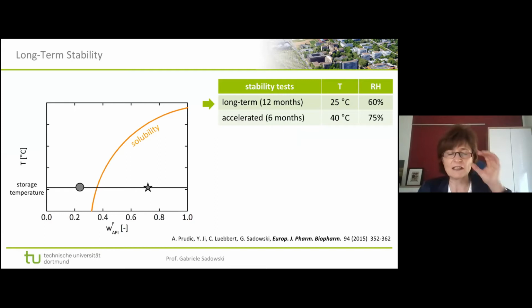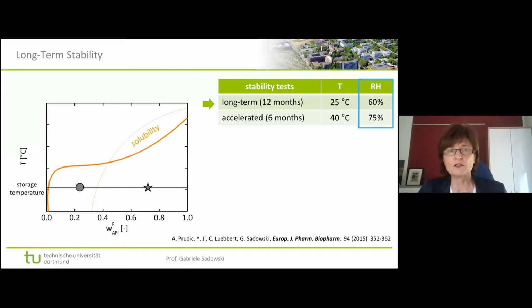And once you have water in a tablet, of course, the API does not want to be dissolved any longer, because it does not want to be dissolved in water. That is where the problem comes from. That means in the ternary system, at these conditions, the solubility line is completely different. You have a hydrophilic formulation on the left-hand side of the diagram, because here you have a huge amount of the hydrophilic polymer. You have a hydrophobic formulation on the right-hand side because here you have mostly the hydrophobic API. So at a fixed relative humidity, the formulations along this axis absorb different amounts of water. The absorbed amount of water is increasing from the right to the left.